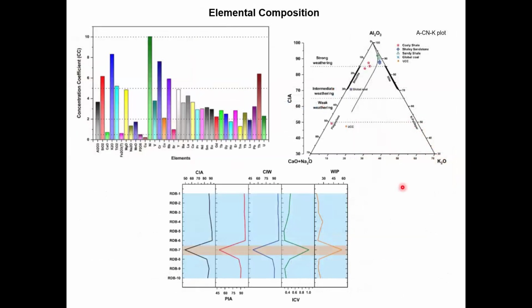Now, coming to the elemental composition, which is very similar to what Dr. Shashwati was showing. We also studied the elemental composition based on trace elements and major and rare earth elements. The concentration coefficient is shown over here, which suggests significant enrichment in some of the trace elements, like nickel, cobalt, chromium, rubidium, thorium, etc. The oxides are also very much enriched in these samples. We also calculated indices such as the chemical index of alteration, plagioclase index of alteration, chemical index of weathering, index of Parker, etc.